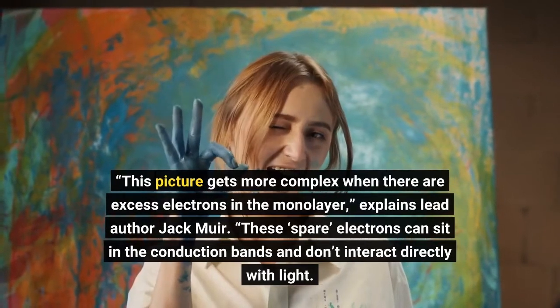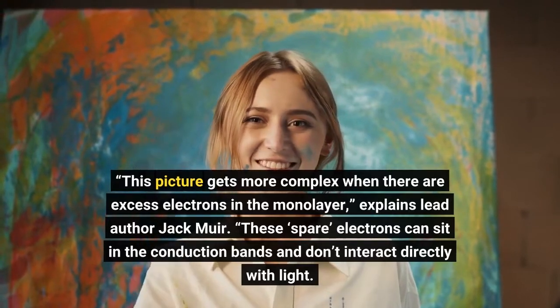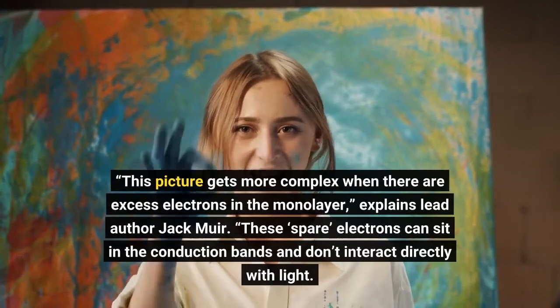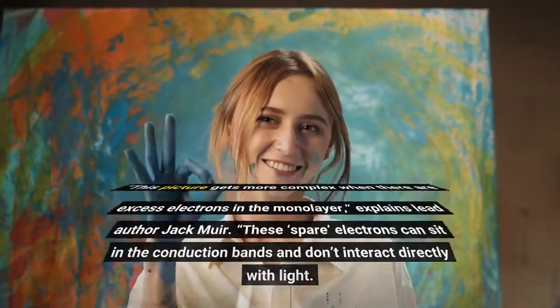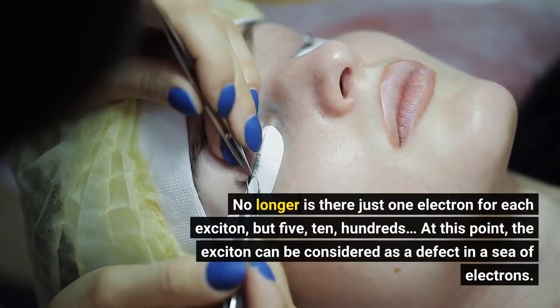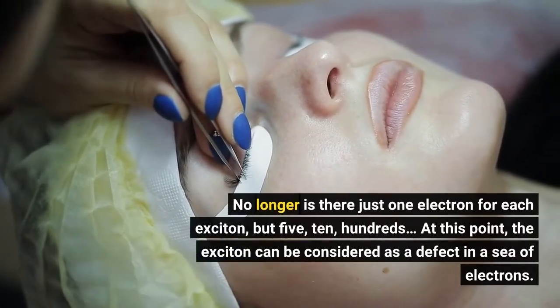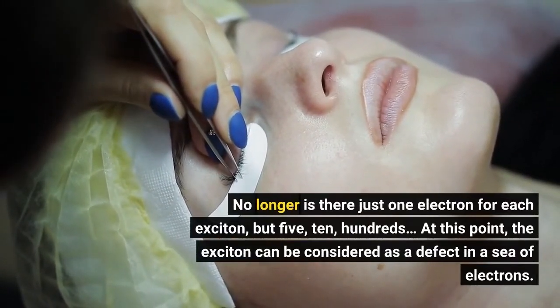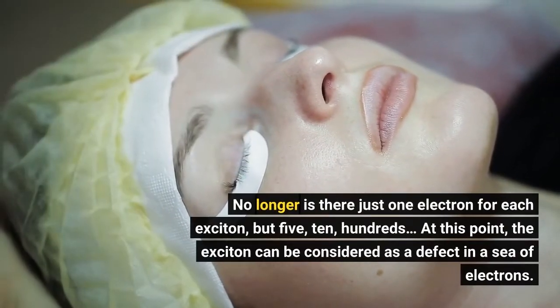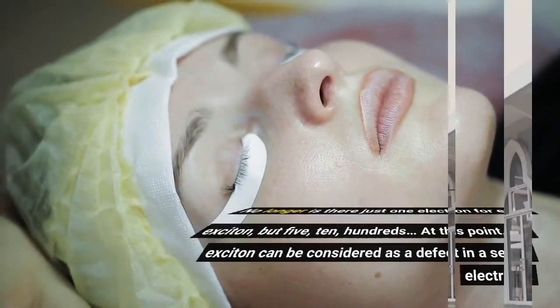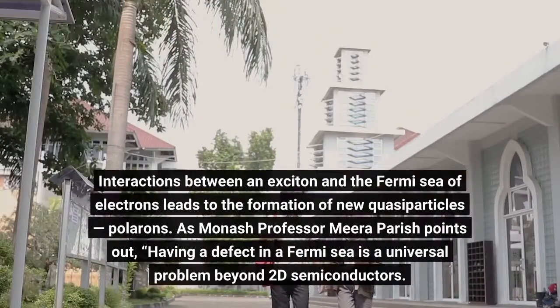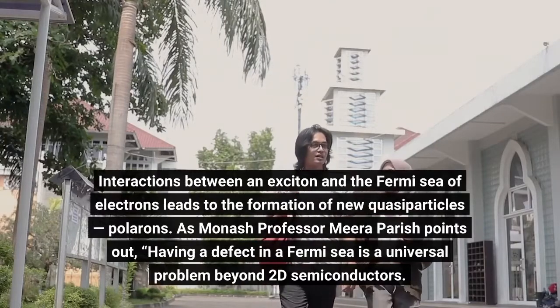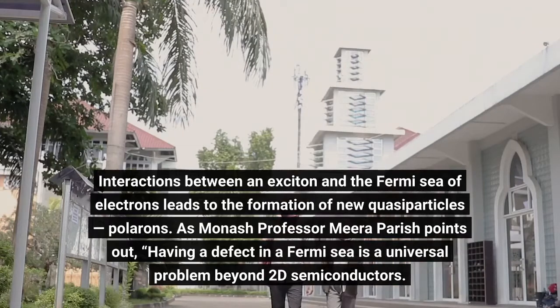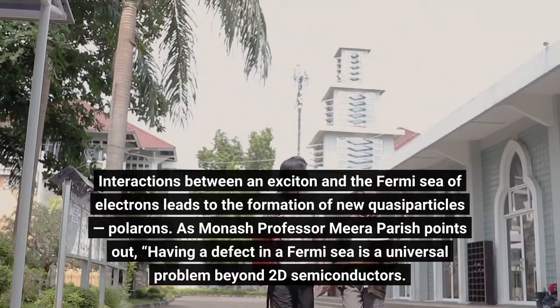These spare electrons can sit in the conduction bands and don't interact directly with light. No longer is there just one electron for each exciton, but 5, 10, hundreds. At this point, the exciton can be considered as a defect in a sea of electrons. Interactions between an exciton and the Fermi sea of electrons leads to the formation of new quasi-particles, polarons. As Monash professor Meera Parish points out, having a defect in a Fermi sea is a universal problem beyond 2D semiconductors.